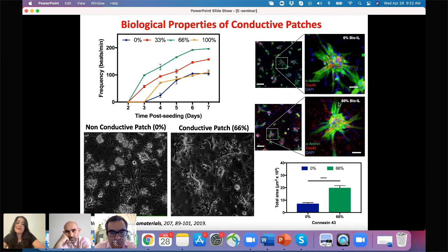And the second panel is the hydrogel seeded with the cells, containing 66% bioionic liquid. As you see here, when we use an electroconductive substrate, we had higher expression of connexin 43, as you see in this quantification data. This increase in the expression of this protein correlated well with the enhanced beating frequency of the cells on this substrate. So the cells respond to the level of conductivity, and at the specific concentration of bioionic liquid, we observe a better function of these cells in vitro.